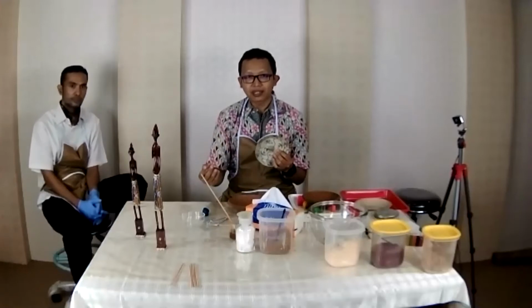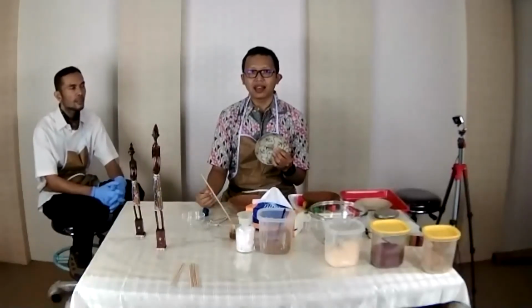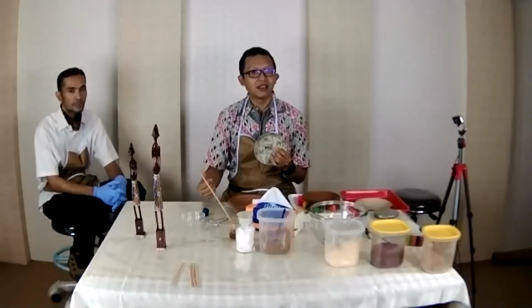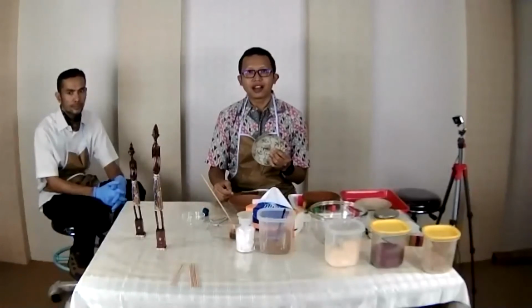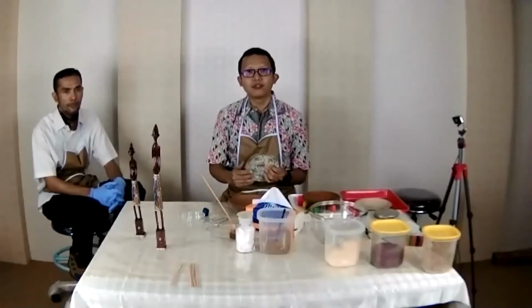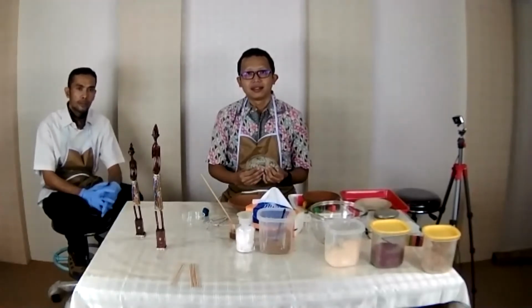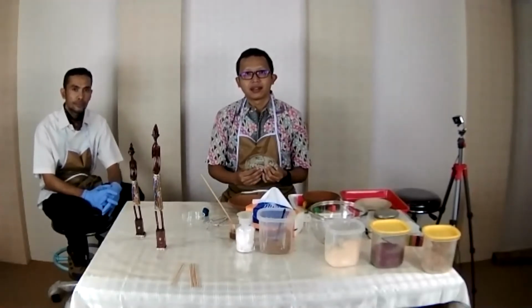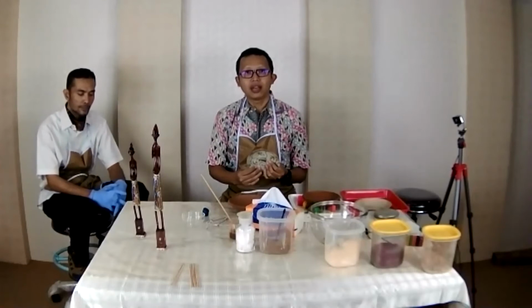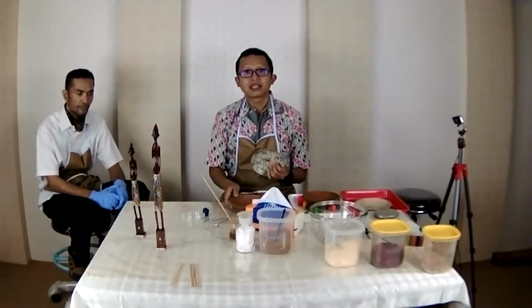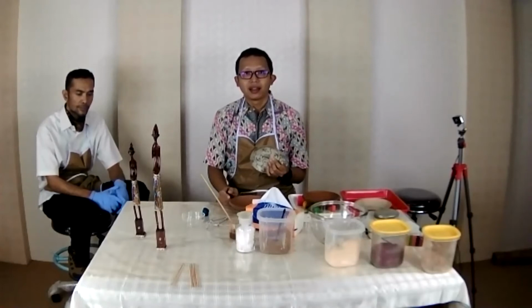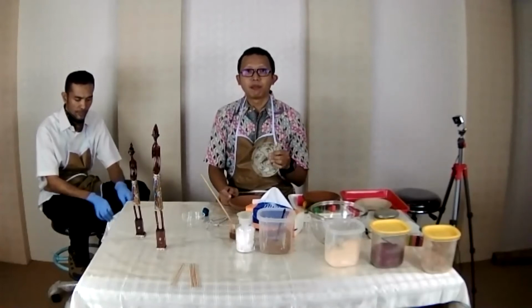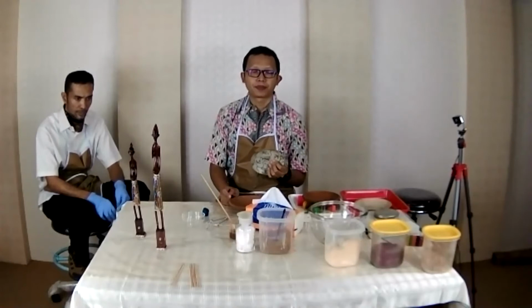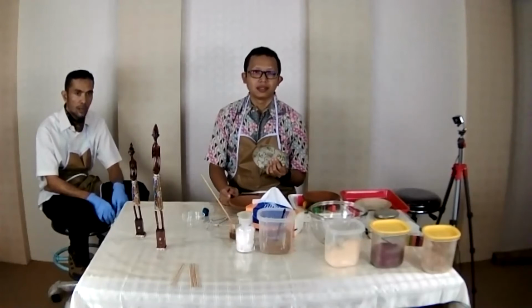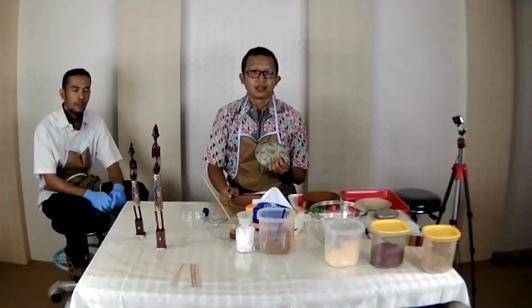Problems usually occur if the fluctuation of humidity is too high, like if you put on the air conditioner during the day and turn it off during the night. So the fluctuation of the humidity of the room will be too high, and this will cause problems. Usually that will cause problems in an artifact joined with natural adhesive.